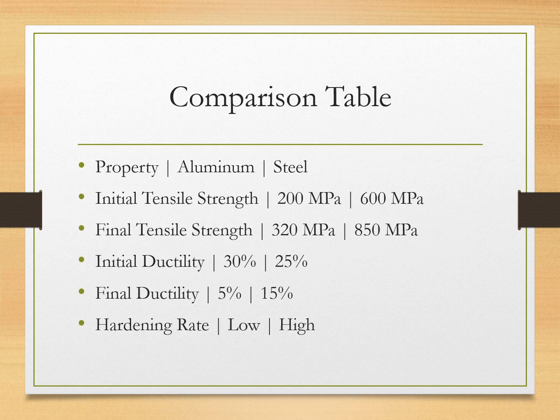So, here's a clear comparison between the two materials. Aluminum started around 200 megapascals and ended around 320 megapascals, while steel started closer to 600 and ended around 850 megapascals. Ductility in aluminum went from 30% down to 5%, whereas in steel, it dropped from 25% to around 15%.